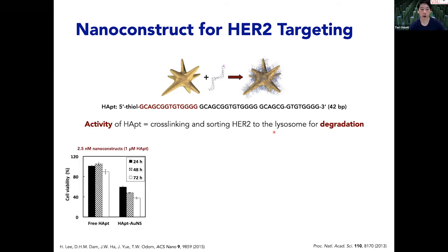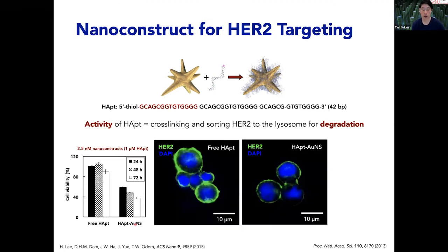And so we first compared the free aptamer to the aptamer that was attached to the gold nanostar. And you could see that there was significant decrease in cell viability or increased cell death when the aptamer was attached to the star compared to the free form, likely because the free form just degrades. And then we compared whether we actually do see a reduction in HER2 that's contributing to this cell death. This is a challenge with biology I found, is that you have to perform like 10 experiments to validate a single outcome. But they're all correlated, and I've learned to appreciate the complexity and all of that.